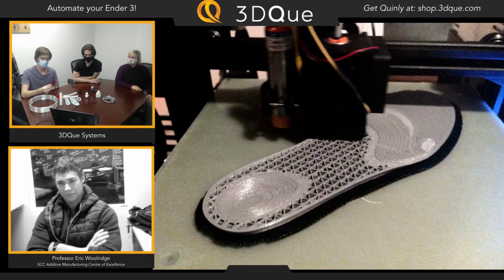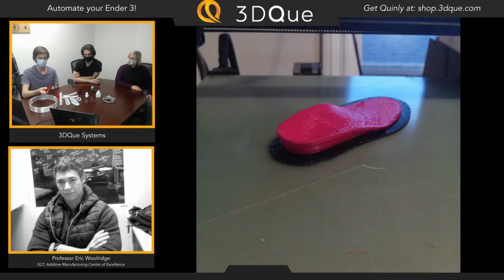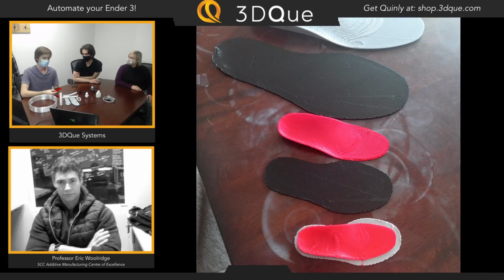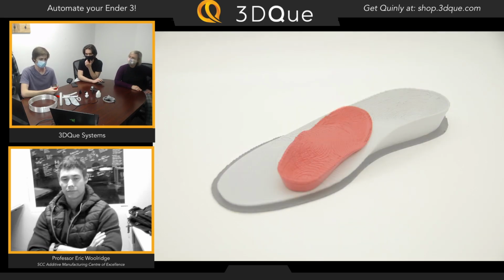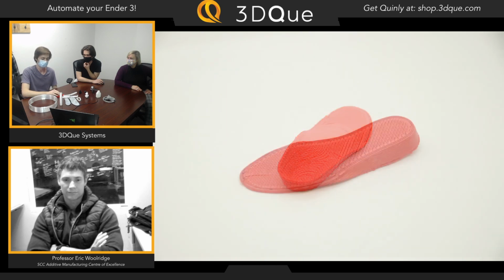That's the same thing with flexibles and the vapor build plates that we use. Before I did all this testing, we were basically telling people, you can't really print TPU on these beds. It doesn't come off. You have to peel it off. It doesn't get pushed off. It doesn't slide off nicely, especially because we were being asked to print really large surface area parts. Having a large surface area connected to the build plate, you'd ram the hot end into it and it would just keep on skipping and make angry printer noises and everything.